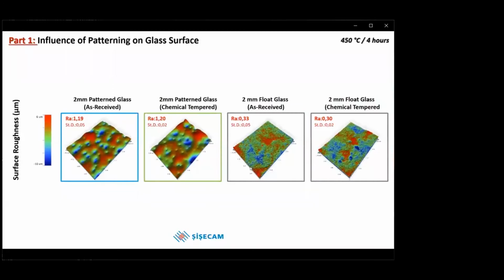When the surface roughness values of patterned and float glass were compared, it was seen that the surface roughness values increased with the application of the pattern on the glass surface. And there was no significant change in the surface roughness values with the chemical tempering process applied to patterned and float glasses.